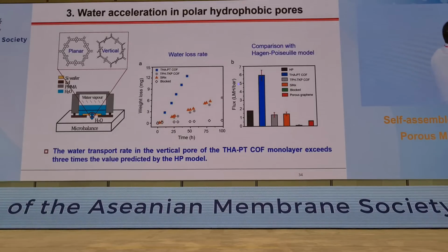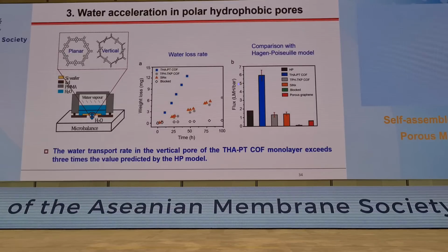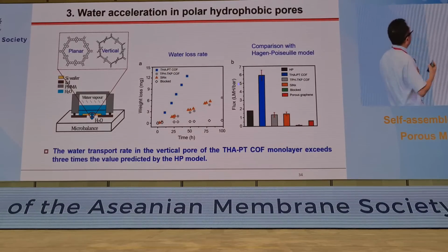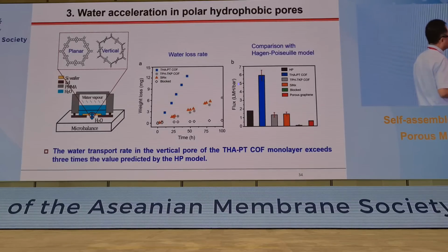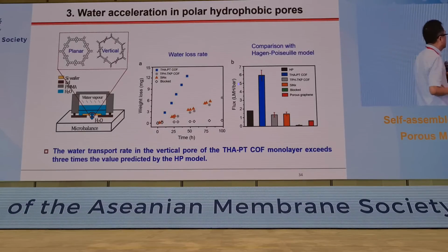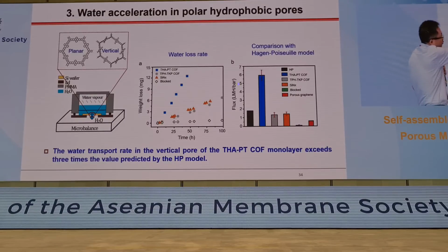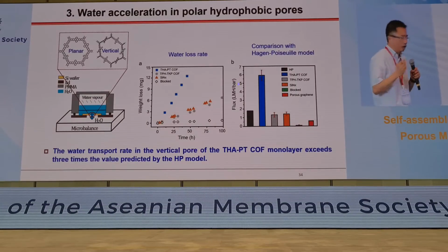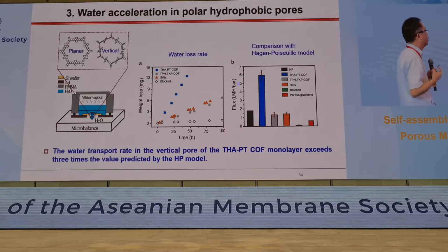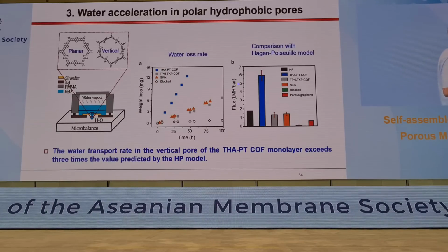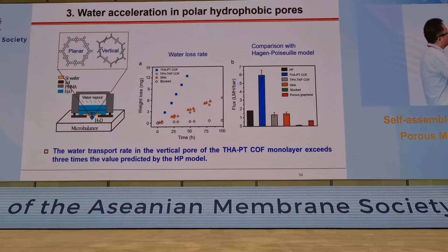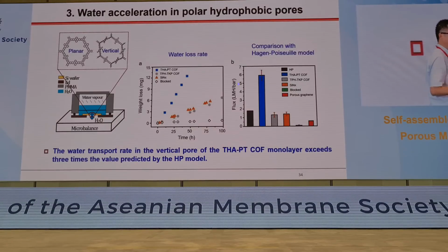We also controlled them as vertical pores, and we found the water acceleration phenomena. We can see from the middle and the right figures that the water transport in the vertical pores exceeds 3 times the value predicted by the Hagen-Poiseuille model.